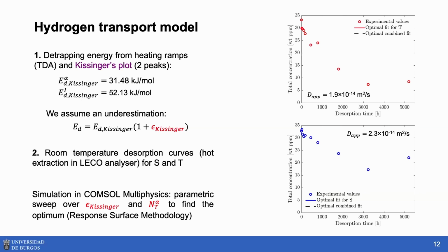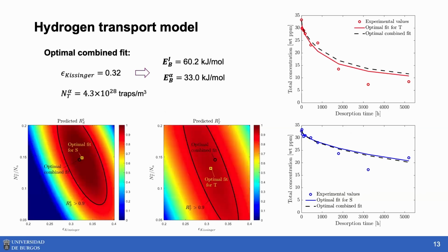So after that, in the second stage, we are using these room temperature desorption curves in 2 orientations, and we are fitting not the trapping energies, but the error that Kissinger is making in this fitting. So with these 2 desorption curves in the T and S directions, we are fitting the Kissinger error and also the density of trapping sites in ferrite. We can fit each orientation, and we can also do a combined fitting. And this is very nice because the combined fitting is very close to the individual fitting for each orientation. This means just that the effect of orientation in these desorption curves is explained by the tortuosity, because the trapping features, the trapping energies and the trap density, should be independent of orientation. So since the global fitting and the individual fitting are very close, we can say that this is more or less accurate.